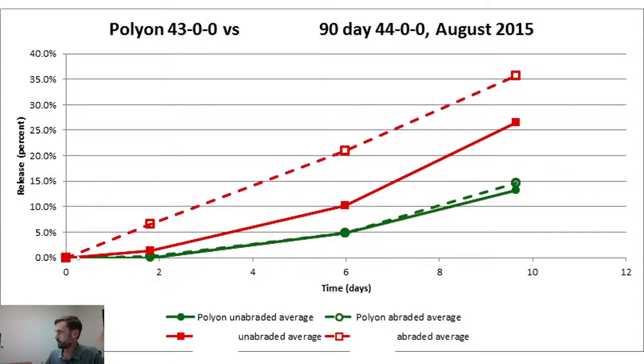As opposed to another material, represented by the red line, where we have the before drop measurement, which has a nice release curve to it, and then the after drop measurement, which is a drastic increase in release speed versus the before drop measurement of this material. So this is not what you want to see. As this material goes through the shipping channels and the application process, it's not going to perform the same in the field as it performed off the manufacturing line. Whereas in this case with Polyon, you can count on Polyon performing the same in the field as it does on the day we manufacture it in our facility.